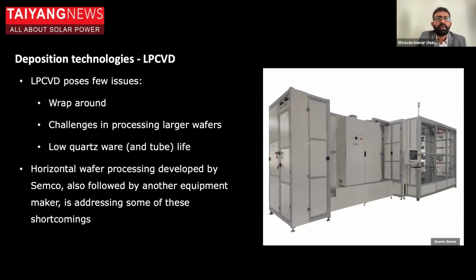But yeah, the general practice for the LPCVD system, in order to improve the throughput, is that they typically employ back-to-back loading. That means 2 wafers are placed in a single slot. This might work for others, but it is especially problematic for LPCVD because the precursor penetrates into the gaps between the wafers and causes a parasitic deposition on the front, which is colloquially called wraparound in the industry.